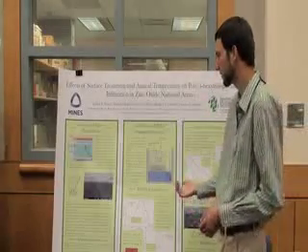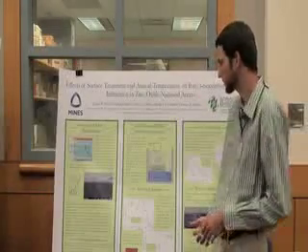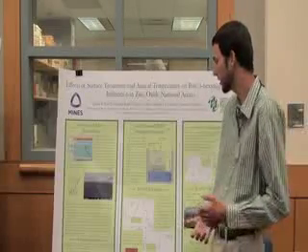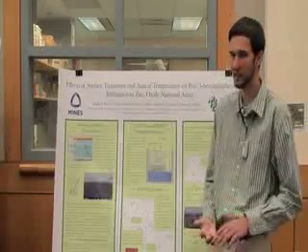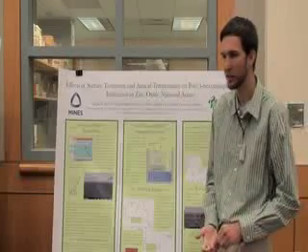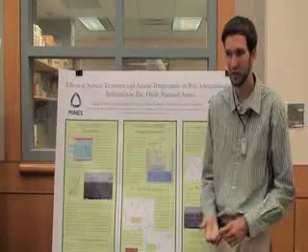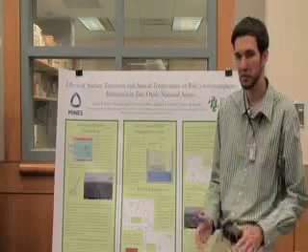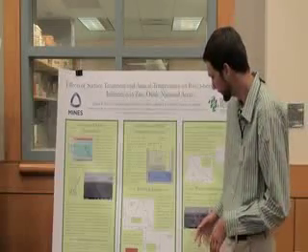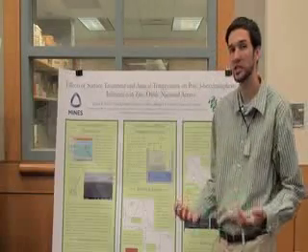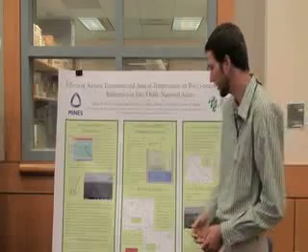So we began with fabricating our zinc oxide nanorod samples in an aqueous solution. We spin a sol gel seed layer of zinc oxide on and then put it in an aqueous solution of sodium hydroxide and zinc nitrate at 70 degrees C. A zinc oxide nanorod array will grow approximately normal to the substrate. And then we spin the P3HT polymer onto the top of that.